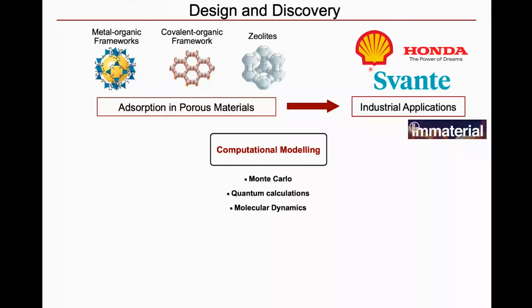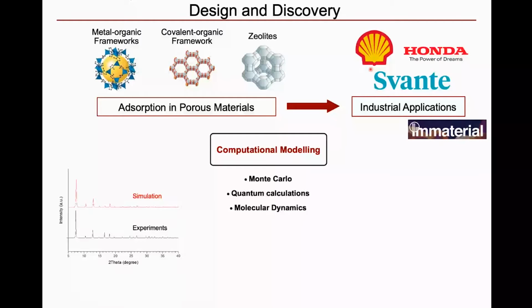So I have to note that macroscopic performance of MOFs is highly related to microscopic structure and dynamics. We can model structures on the computer to shed basically more light on the crystal structures. This is particularly important on materials where it is difficult to obtain single crystal and the structural information always needs to be refined based on, for example, powder X-ray diffraction results.